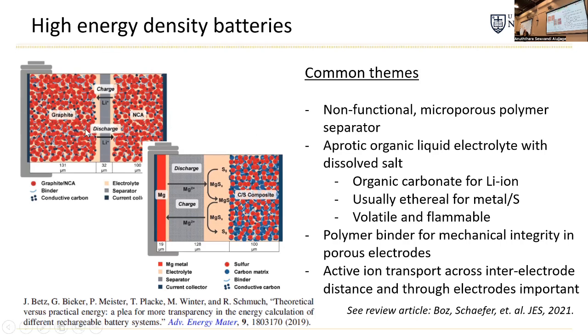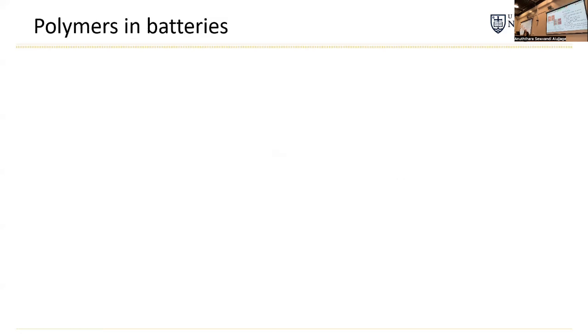And the rate capability of these cells is limited by both electron transport, but also the active ion transport. And it's important that the ions don't just move between the top surfaces of the electrodes, but that the ion can actually get within the depth of the electrodes fast enough. And if you're interested in limitations on ion transport, we wrote a review article in JES a few years ago on this. We really combined a lot of literature.